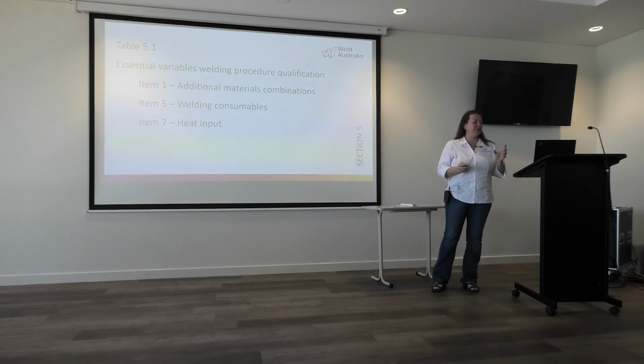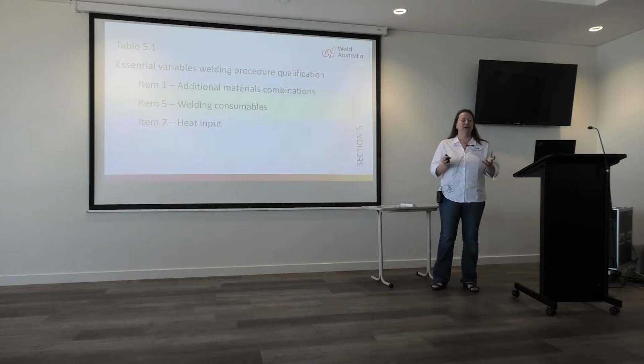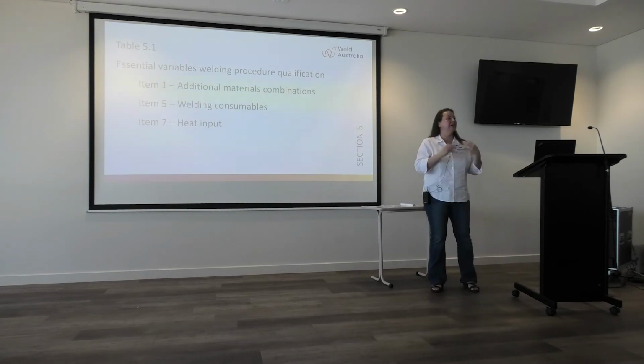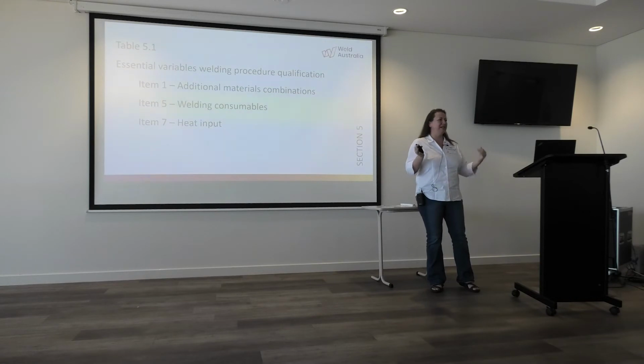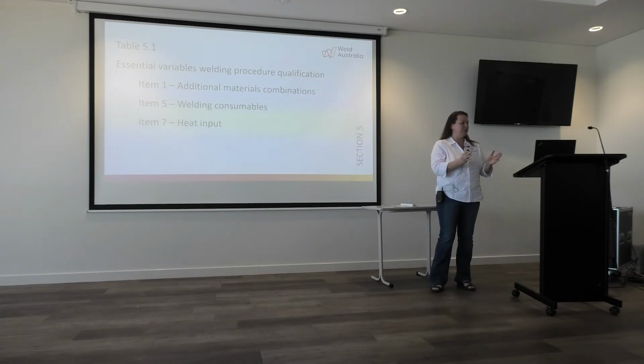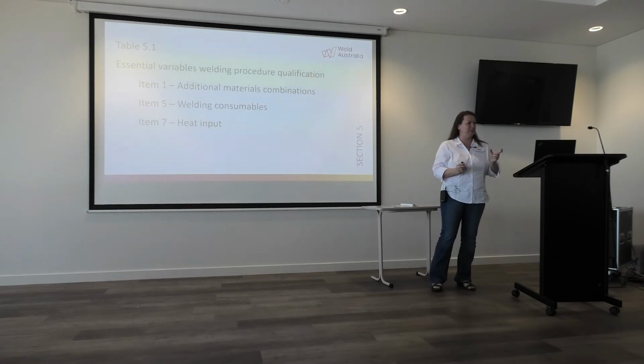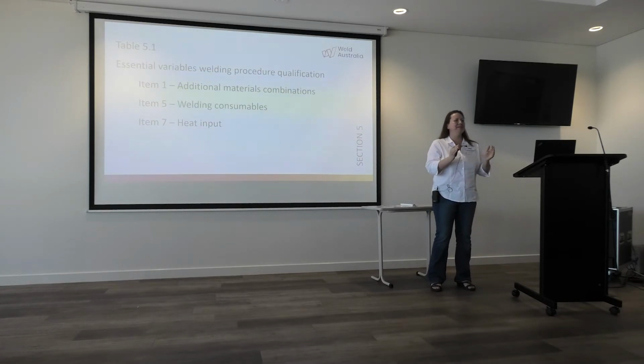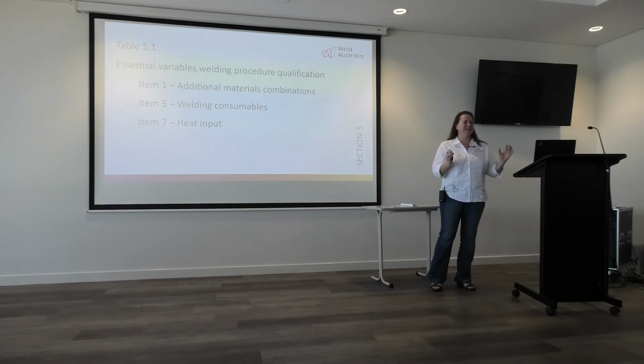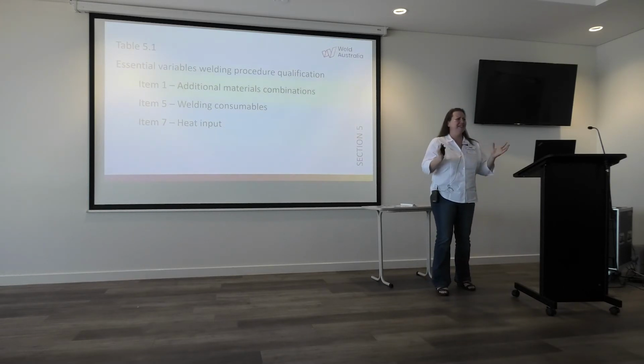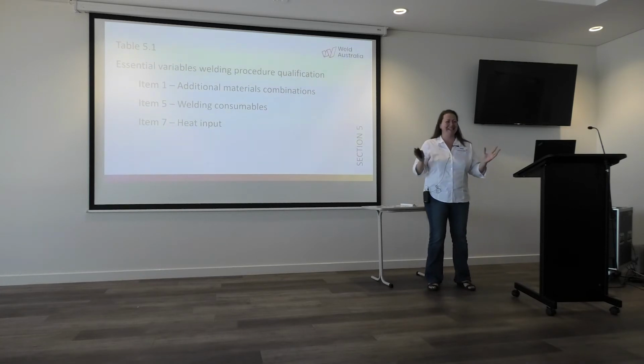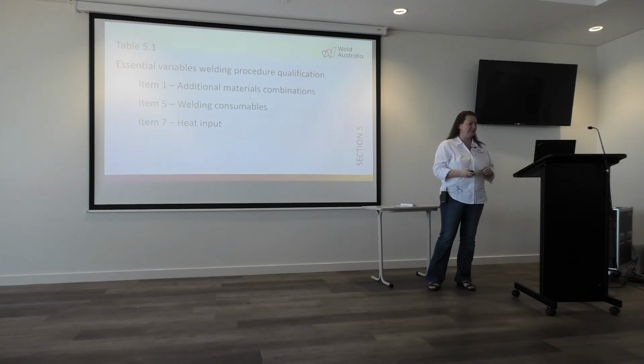And then the creep range was added for the heat input for gas tungsten arc welding, which was previously introduced for MMA. And then the requalification range, the previous heat input range, if you don't have toughness testing, was plus 80%, minus 50%. And that's been narrowed down to plus 30%, minus 25%. So it's not as narrow as the ISO range of plus or minus 10% because people were going to throw tantrums. But we narrowed it down to something more applicable. The standard was so wide you could drive a bus through it. So it's a work in process to update aspects to meet the technical requirements.